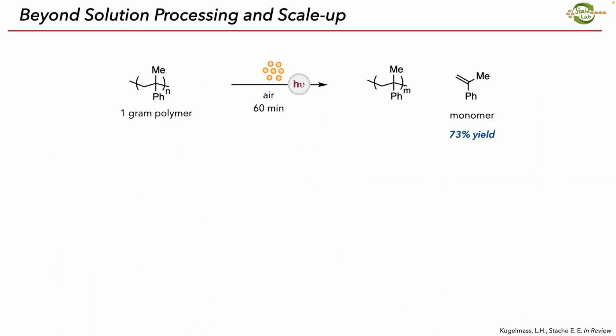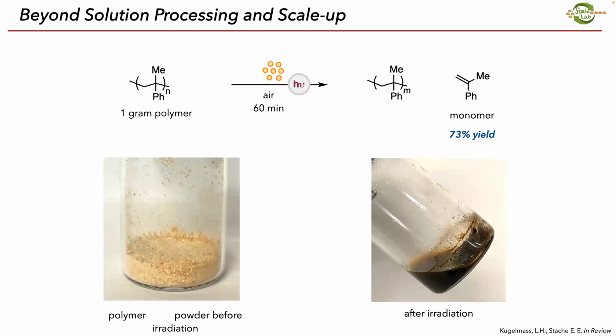I showed you a very tiny film, like 10 milligrams. Liat has been able to scale this up to 1 gram. She hasn't gone past that. We think it'll be pretty scalable. And in this case, she doesn't have to solution process the polymer. She just has the polymer, she adds the nanomaterial, she stirs it up, hits it with light, and you can see all this liquid here is now monomer.